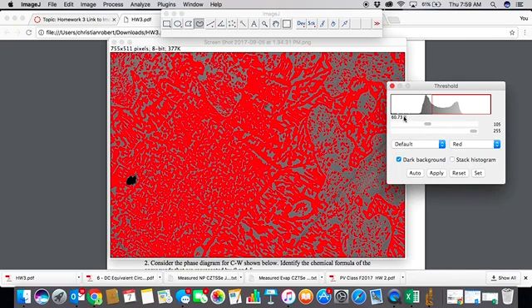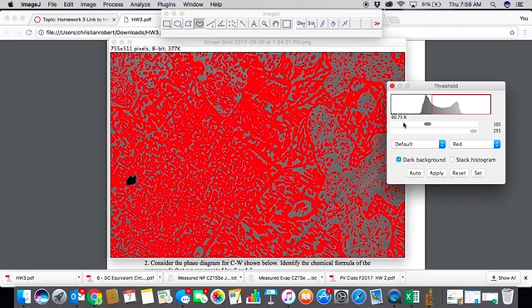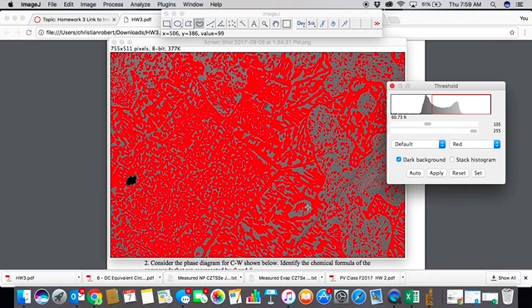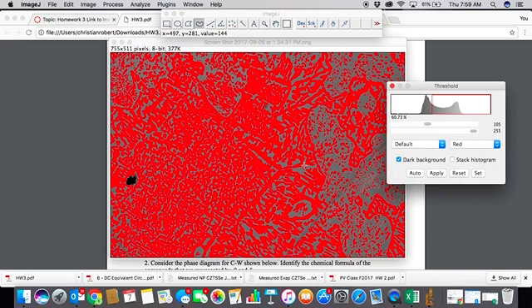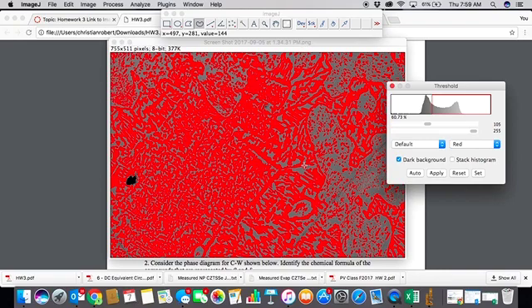And now what that does, it tells you that, if you see this number here, 60.73% of your total pixels are white. And then the rest are gray. And so you can use that. That corresponds to an area fraction. So the total area of this image, you can assume that that's the same as the volume fraction. And then you'll need to use the densities to figure out the mass fraction. So that's a pretty big hint on how to do problem one. And if you have any questions on how to use ImageJ, ask one of the TAs, and they should be able to help you out.